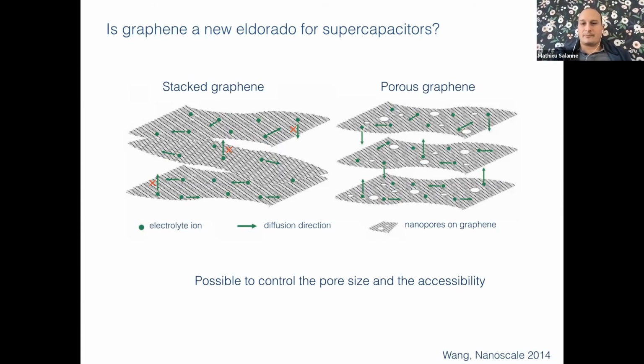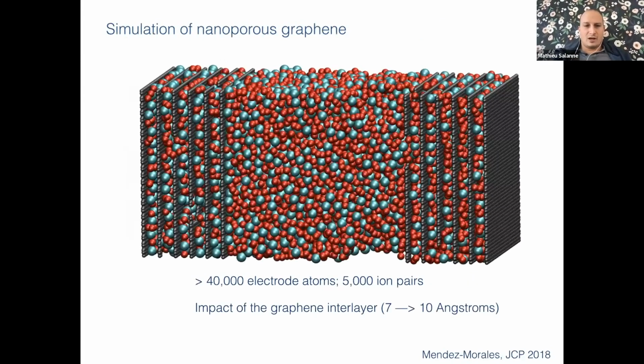because people were hoping that it would be a perfect material. So on our side, we did a simulation of this system, which is quite large even for classical simulation, because we have more than 40,000 electrode atoms, which have fluctuating charges. We have 5,000 ion pairs. So this required the use of supercomputers, of course. And we studied systems in which we have systematically varied the graphene interlayer from 7 to 10 angstrom.